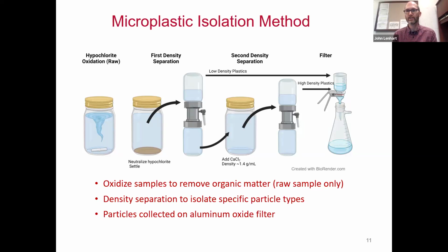We do density separation to get the low density plastics, so they float or accumulate at the top of the water. We can do a density separation using a two-chamber separator. We then change the density of the water to isolate the more dense microplastics, so 1.3, 1.2, 1.4 kilograms per liter. Those we collect and add to the system with our low density plastics. We go through and filter this and collect it on an aluminum oxide filter.